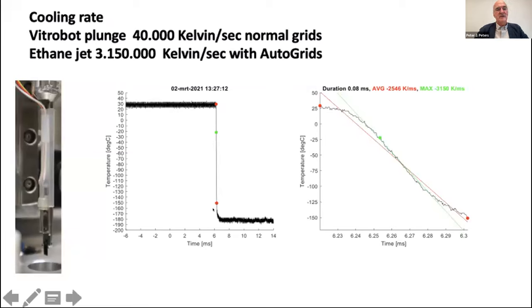Here you have the vitrification measured by this device. This very small distance is seen better here. Now you can see the actual cooling rate, and we measured that this is about 3 million Kelvin per second. We are talking about an autogrid that contains the clip ring already. Compared to the Vitrobot, where you have worked with naked grids, they have a cooling capacity of 40 in the Vitrobot. So you have an incredible amount more vitrification capacity. And that is good news.